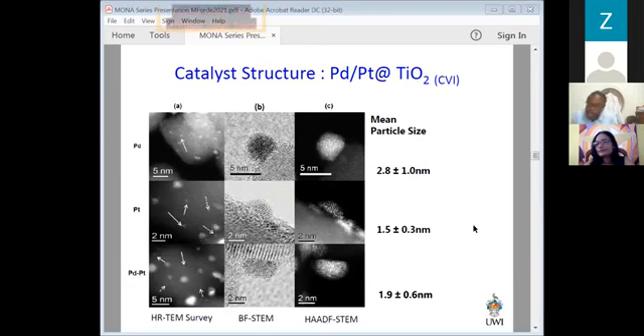In terms of MOFs, no. What people have been doing with MOFs, though, is making nanoparticles from the MOFs themselves. So decomposing the MOF and ending up with small nanoparticles, which they can then deposit on something else, which is an interesting strategy because it seems roundabout to me to make a beautiful MOF and then just degrade it